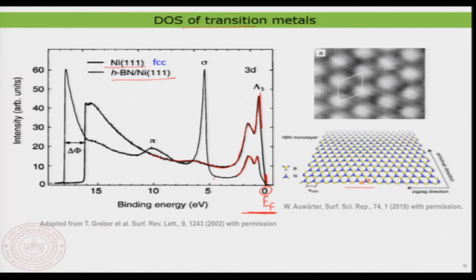But after that, about 5 electron volt, you can see there are strong bands that are actually coming from the material itself. So you can now clearly understand, just by comparing the density of state of the nickel and also the density of state of the HBN deposited on top, how the density of state changes when you deposit something on the nickel. So this is basically how the density of state would look like for different materials. You can clearly do it for any different type of material,